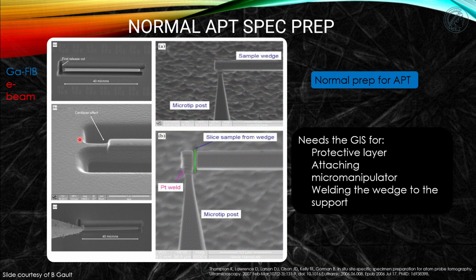So the sample, effectively you produce the cantilever, you then attach it to the needle, and then you chop off the edge of the Toblerone, and this can get you multiple samples from this linear object, so your throughput can be very high. So we're going to use the gas injection system to do a protective layer and to attach it for each of the welding operations, and effectively this will enable us to get this.